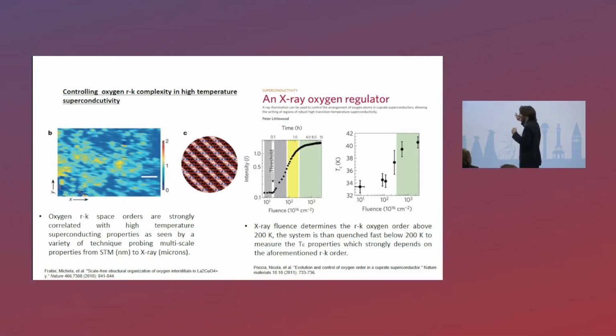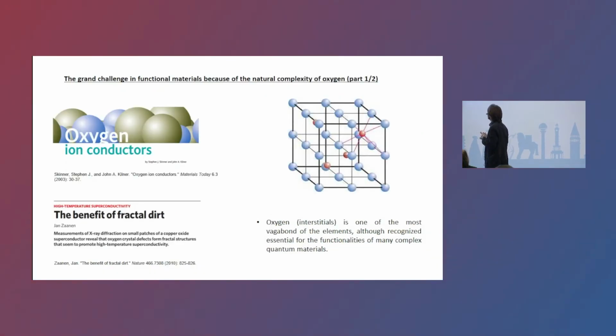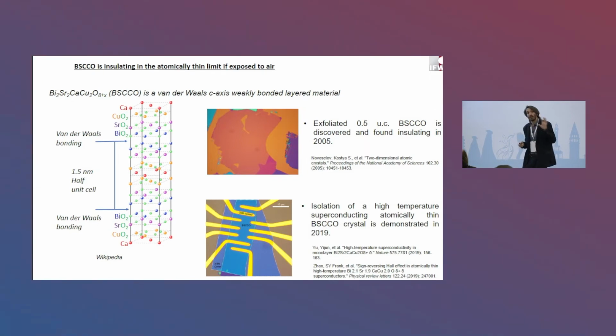You can also start to control this oxygen ordering if you put yourself close to the temperature where the oxygen starts to be mobile, which is 200 Kelvin. Then you apply X-ray flux, and you see the K-space wave vector related to the oxygen ordering increasing in diffraction. Then if you quench, depending on which stage of the order you are at, the system at low temperature will show different TC, increasing with the K-space ordering of the oxygen interstitial. So you can control it. This just shows how sensitive the systems are to oxygen, and how important it is to understand deeply what the oxygen is doing.